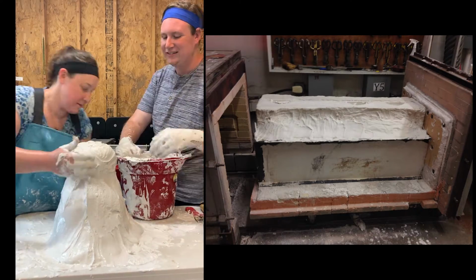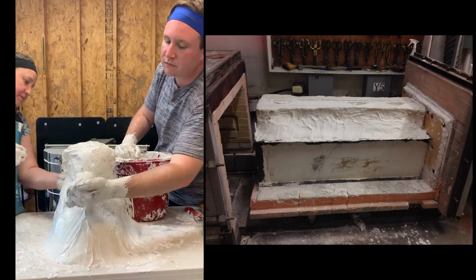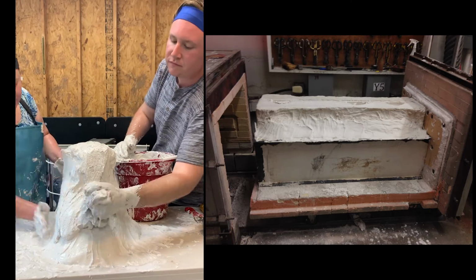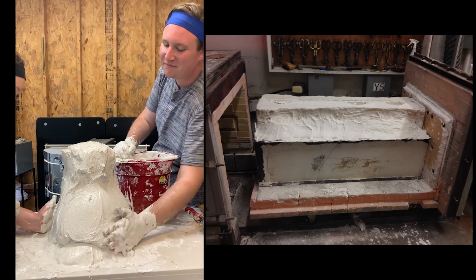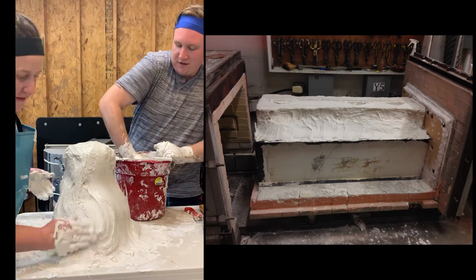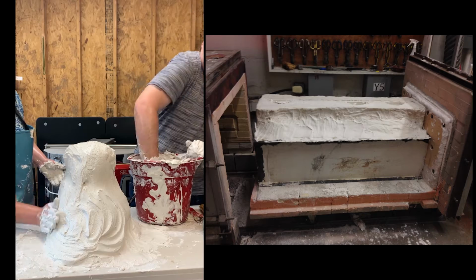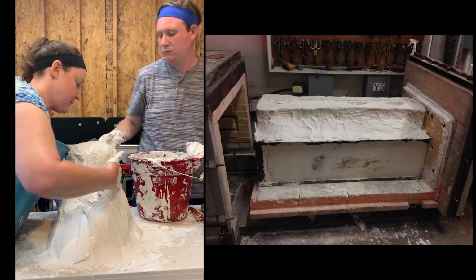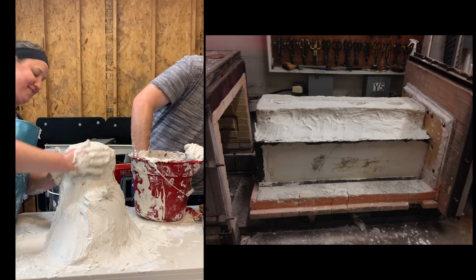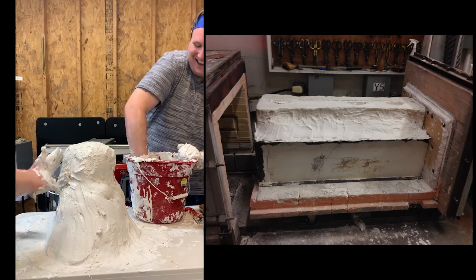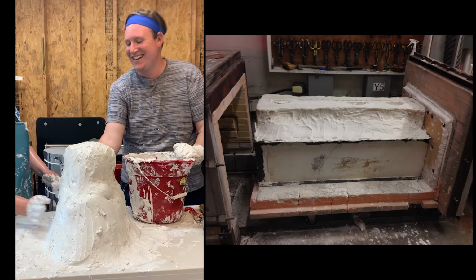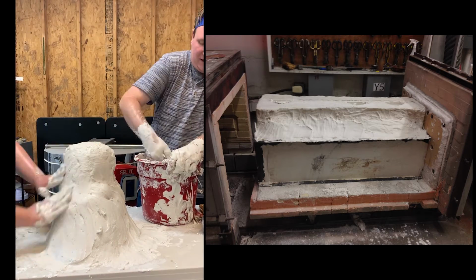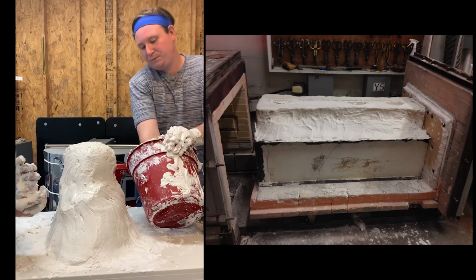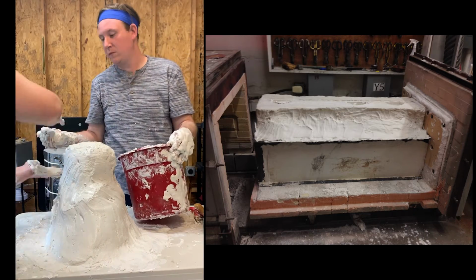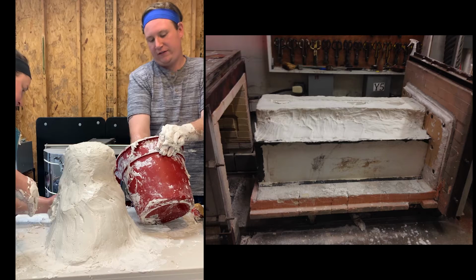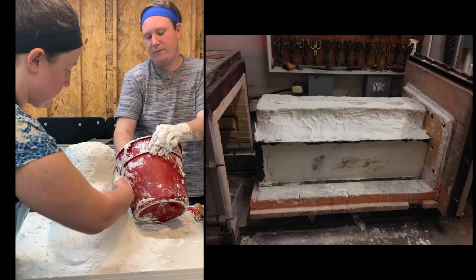Here's the mold loaded into the car kiln. It took a forklift to move the mold into the kiln, and at this point it weighed over 600 pounds. I then welded angle iron around the mold and added another layer of plaster silica, making the total weight of the mold 900 pounds. This was in the kiln for 8 weeks, and the mold came out perfectly. We did not have any problems with the mold breaking during the casting.